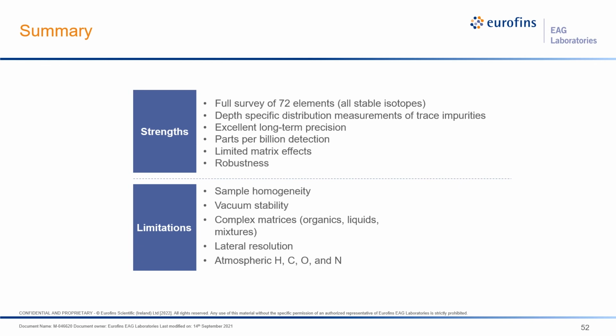Like any other technique, it has limitations. You have to deal with sample homogeneity if it's not very homogeneous. And it has to be vacuum stable, so for organics, liquids, and matrices, you have to be very careful. And it doesn't provide the lateral resolution needed. And because it is not a high vacuum technique, the atmospheric species like hydrogen, carbon, oxygen, and nitrogen need to be treated very carefully. But EAG does have a complementary technique for each of those aspects. We have ICP-OES and MS techniques, we have laser ablation techniques, and we have IGA techniques to address those challenges.